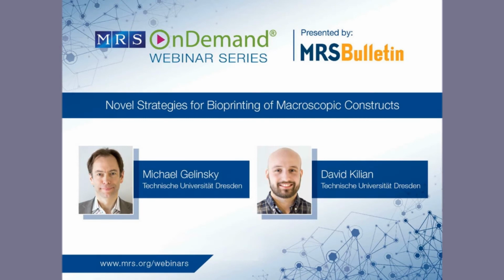So the strategies to tackle this are, first of all, the macropores that you saw in most of the introduced studies and the introduced constructs of several hundreds of micrometers, basically to ensure the access to oxygen and cell culture medium. However, therefore, high viscosity of the material is required, so to really keep those pores and the macroporous structure even in horizontal range.